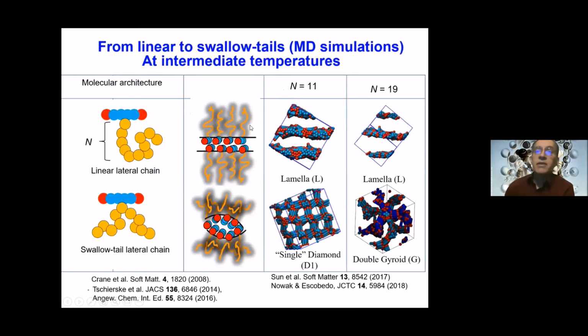But if you make them bifurcated, now it's the exact same number of beads. So that means that they need to occupy the same amount of volume. But now, because they are shorter, they cannot extend farther from the interface. So they have to find the same volume, but they will do it laterally. You have to find it around them. And the only way they can do it is by curving the interface, creating basically eventually tubes. So once you have formed tubes, if the tubes intersect, that's when you create these network phases. So now this explains qualitatively why we see these changes.